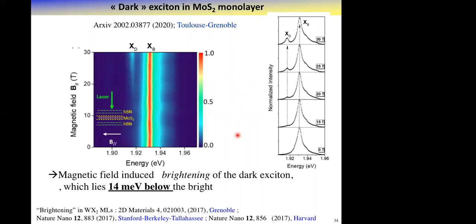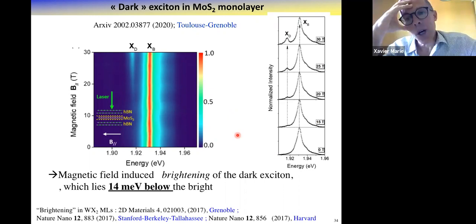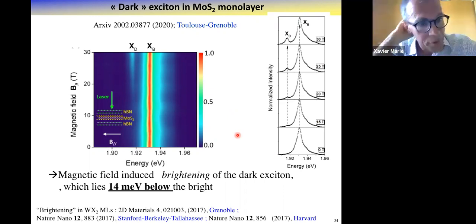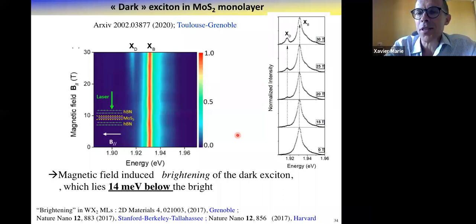I'm here. So I was curious about whether the dark exciton increases the PL lifetime at low temperature like it does in II-VI quantum dots, or if it just affects the direction of the emission. So if you cool into the lowest state and it's dark, does that affect the lifetime? Yes. So we expect to have this effect, though we have not measured it, because under 30 Tesla it's not easy. So we have measured the dark exciton lifetime without magnetic field. And the dark exciton lifetime, in the best sample on WSe2 monolayers, is of the order of 1 nanosecond.